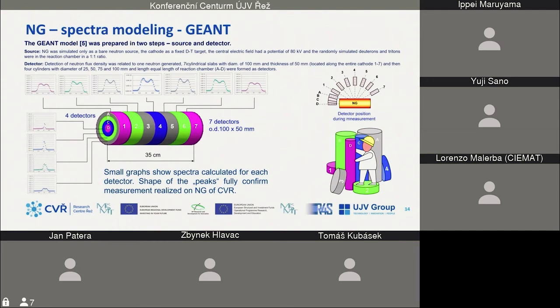There is a result of our spectra modeling. As you see, there are several detectors modeled by the GEANT code. In the middle, or in the perpendicular direction, we got the same shape of the spectrum, which confirmed our measurement. That's perfect. So we finally have a tool for modeling of the spectra and comparing with the experiments.